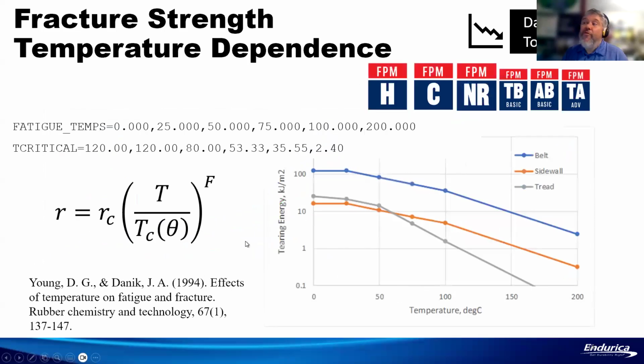So now, of course, when you're doing this type of simulation, not only do you need the hyperelastic, the crack growth curve, the crystallization behavior, but now we also need to think about, well, how does the crack growth rate curve depend on temperature? How does the tire age? How does the tire respond with aging of the material? And we have tests for characterizing all of those things.